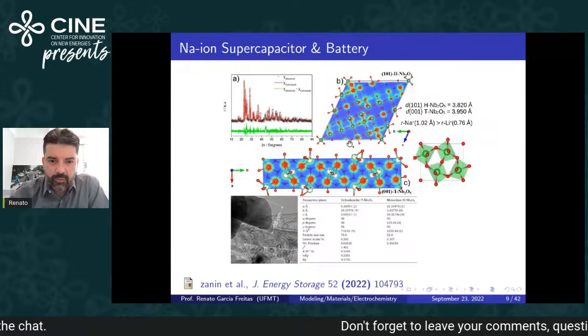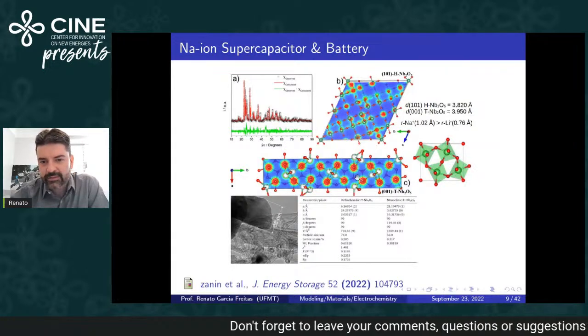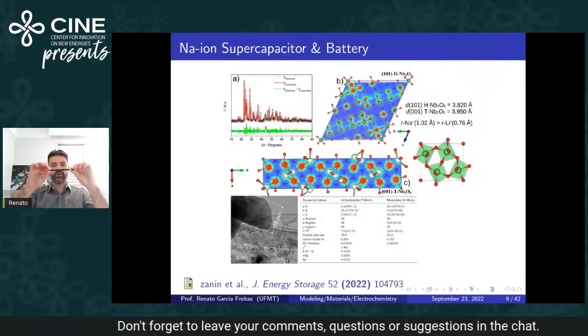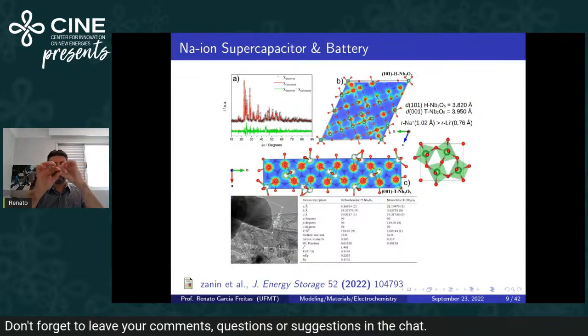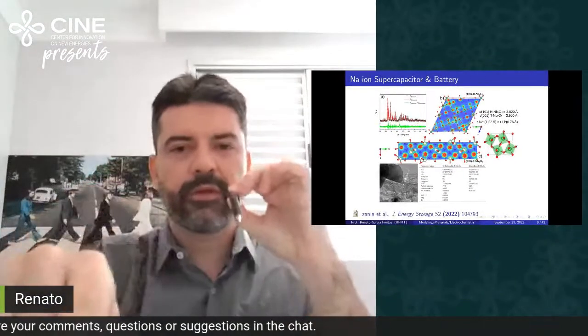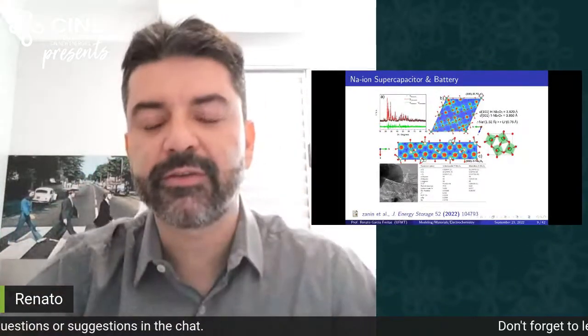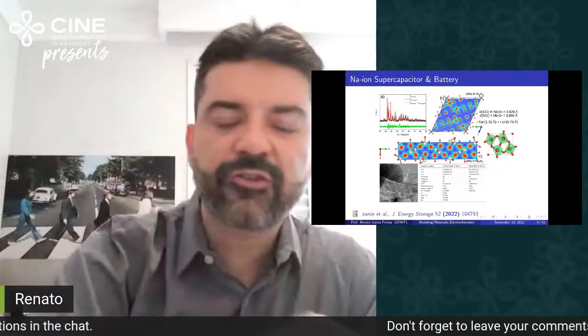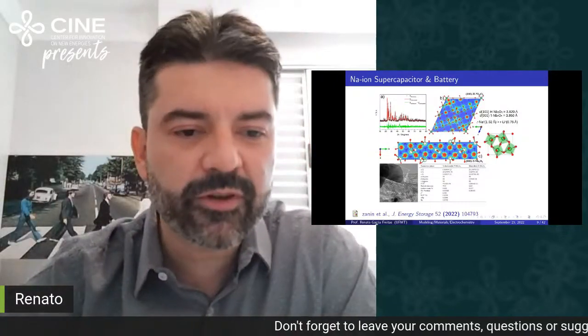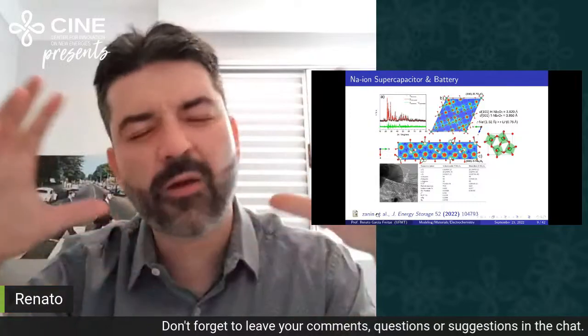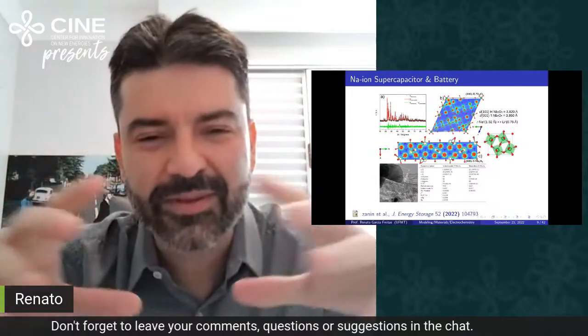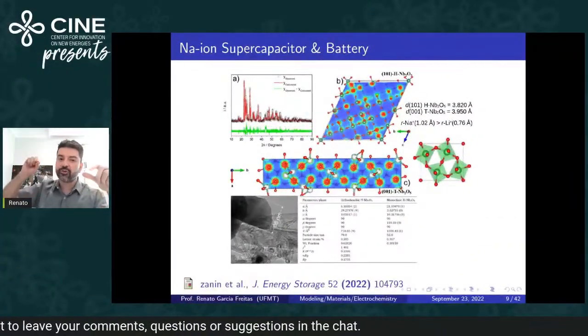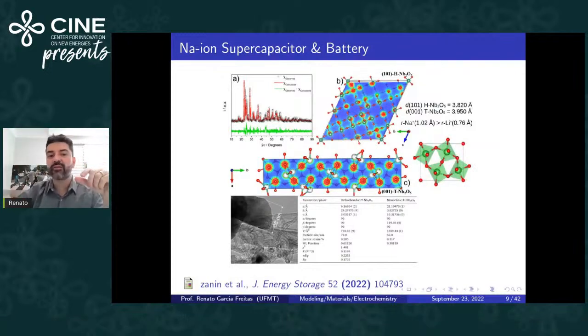What's the main point here? If you take a look at the c-axis of the structure, we have the 001 orthorhombic niobium oxide. If you take a look at this part, you see the channel where we can insert and, during the charge and discharge, extract the sodium ion. And Professor Zanin and his team made a very special kind of material, this one, because it's possible to use the sodium ion in the supercapacitor, pseudocapacitor in this case, and in batteries as well, as you see. And why is sodium so important?